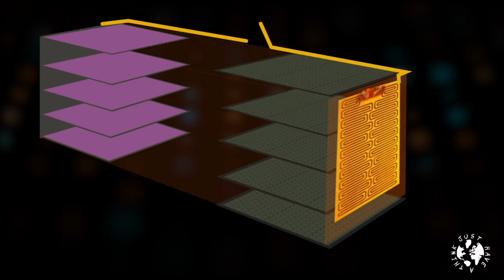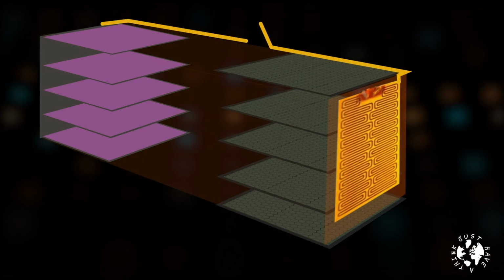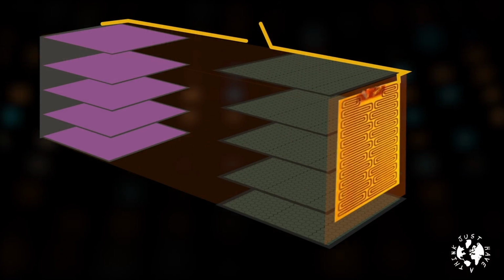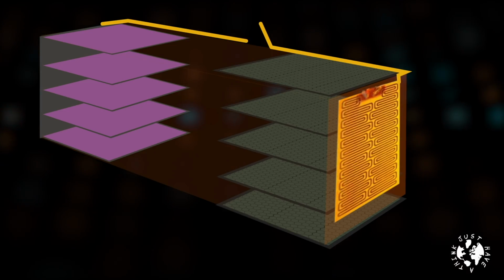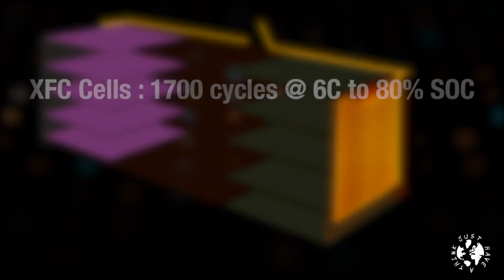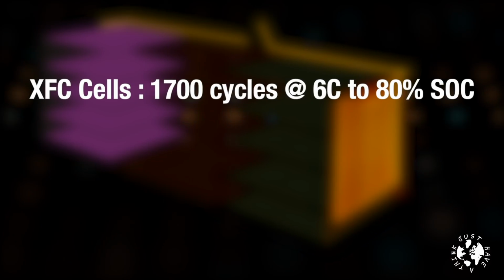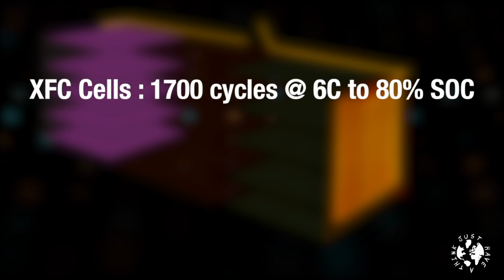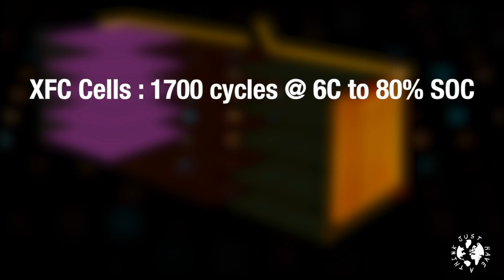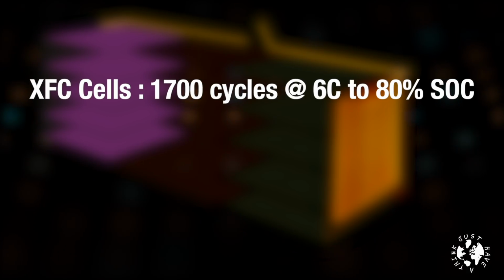The researchers found that by forcing the cell temperature up to charge at 60 degrees Celsius and then causing it to discharge at around about room temperature, the cell sustained 1700 cycles of 6 times faster charging to 80% state of charge with a 20% capacity loss. For comparison, a control cell charged at 6 times normal charge speeds directly at room temperature only survived 60 cycles.